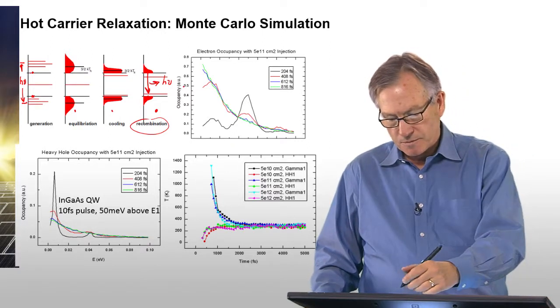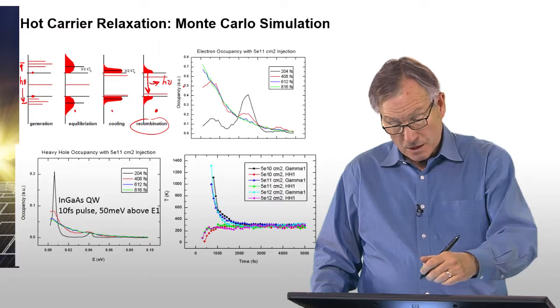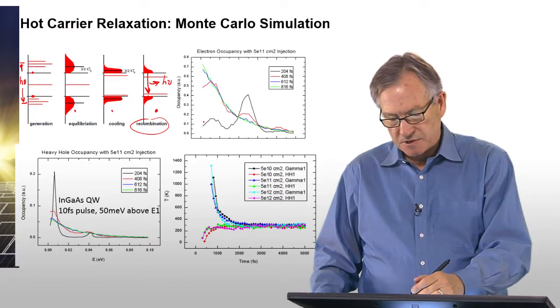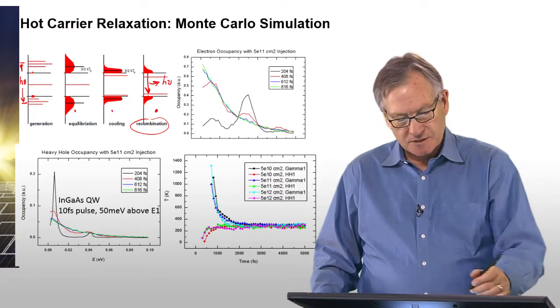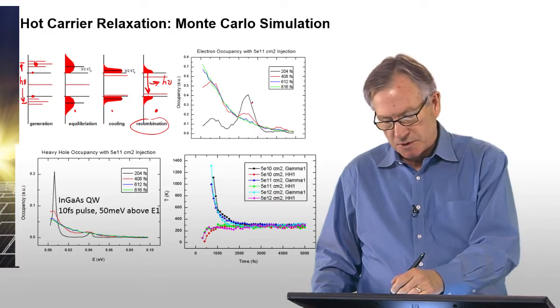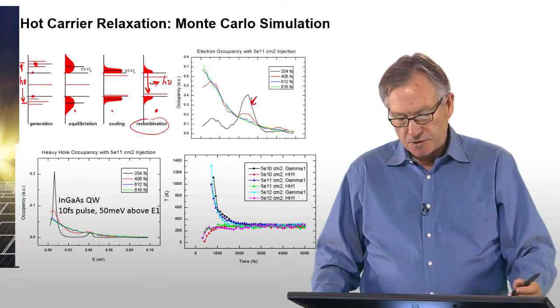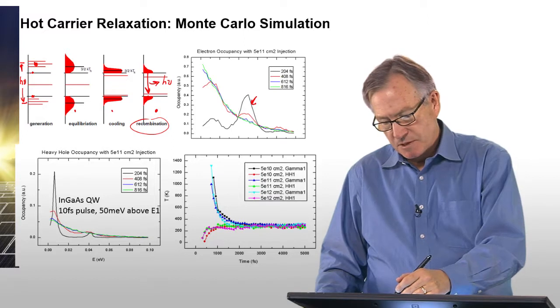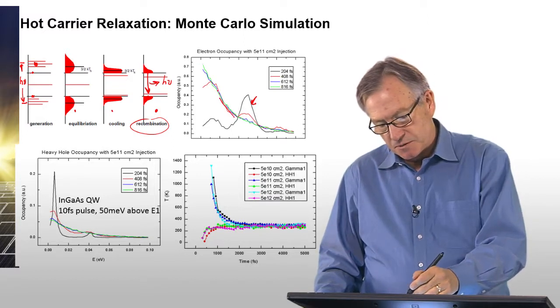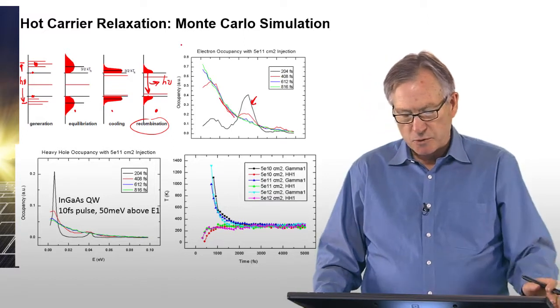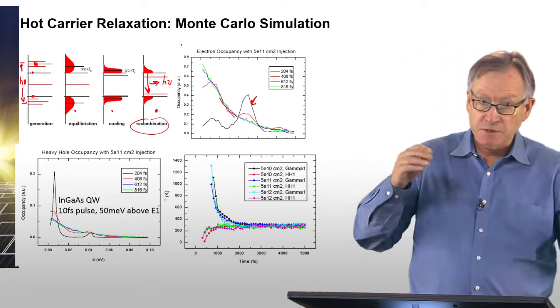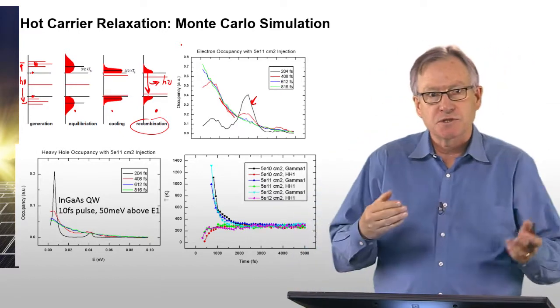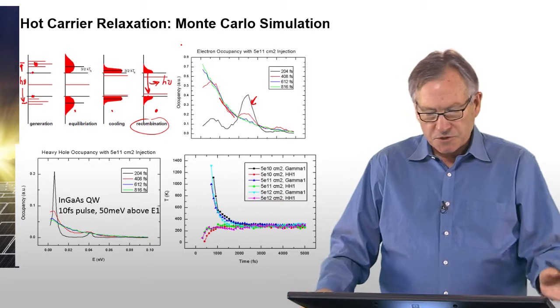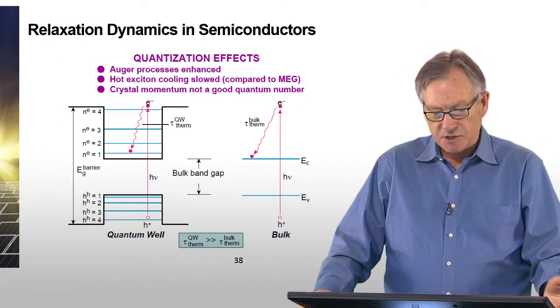And this is just Monte Carlo simulation showing that effect going on. This is, for example, the electron distribution function at snapshots corresponding to this, which corresponds to what's called an athermal distribution. And then after a short time, this basically evolves into a sort of Maxwell-Boltzmann tail. And that's all due to carrier-carrier interactions, which are very fast. So this is sort of the hot carrier dynamics as simulated.